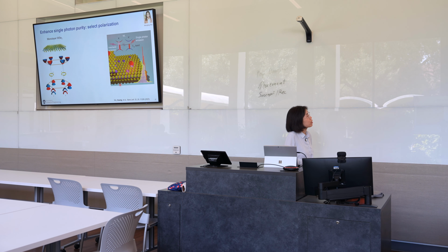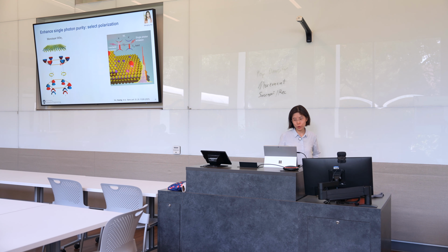The first strategy is to select polarization. We know that for monolayer tungsten diselenide, there are K and K prime valleys. They correspond to different circular polarizations of light. Now you can imagine if we use co-circular polarization for excitation and detection, meaning you use the same polarization for excitation and detection, you inevitably excite this band-to-band transition. This will constitute a large classical background. But if we use cross-circular polarization, meaning a different circular polarization for excitation and detection, this limited valley hopping will effectively suppress the classical background. And potentially you can improve your single photon purity.